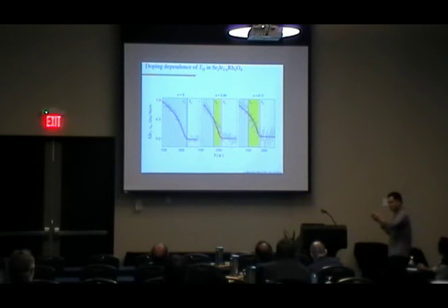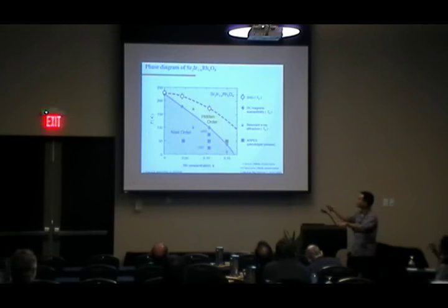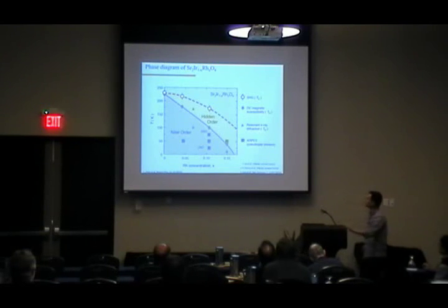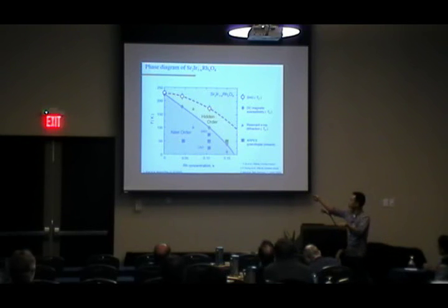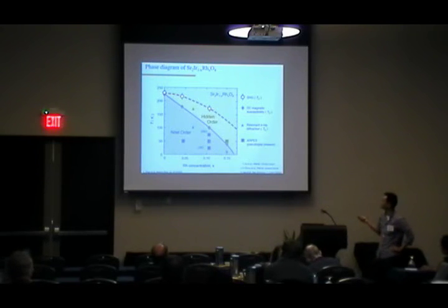But if you compare this to where the actual Néel transition lies, you find that this T omega systematically occurs at higher temperature than the Néel temperature. And so this phase boundary looks suspiciously like a pseudogap boundary. Photoemission studies have yet to pin down T star, the pseudogap temperature, in this material, but if you ask me at the break or afterwards, I can tell you a little bit about work we've been doing on cuprates to establish that relationship.